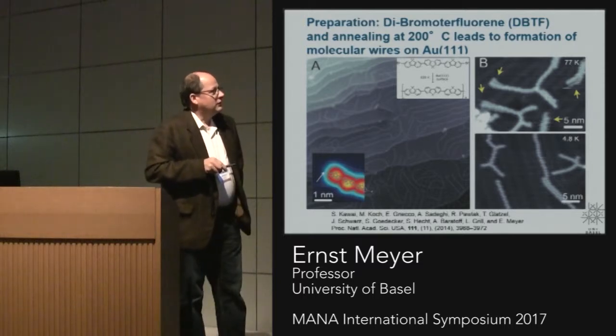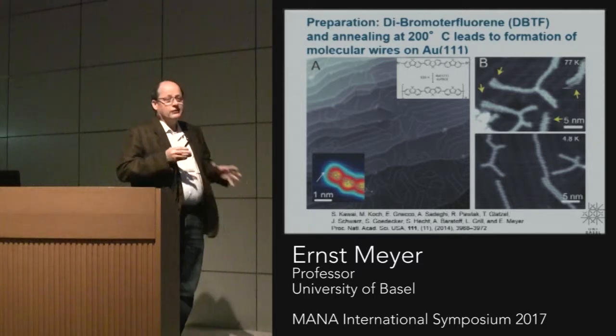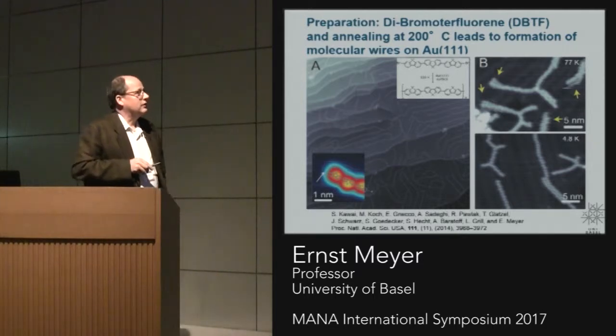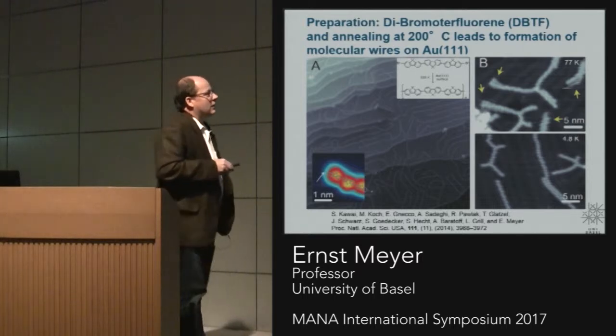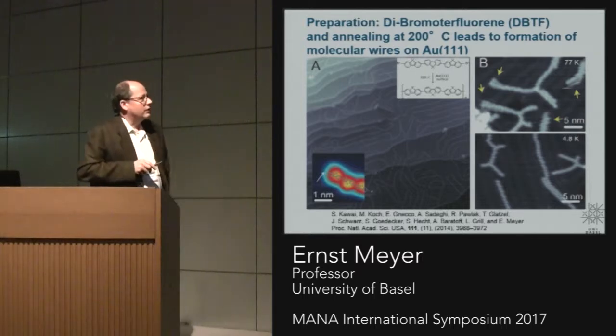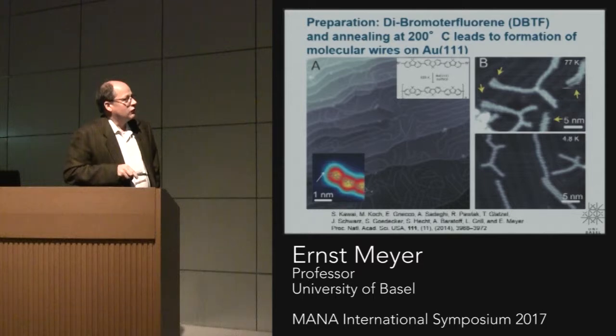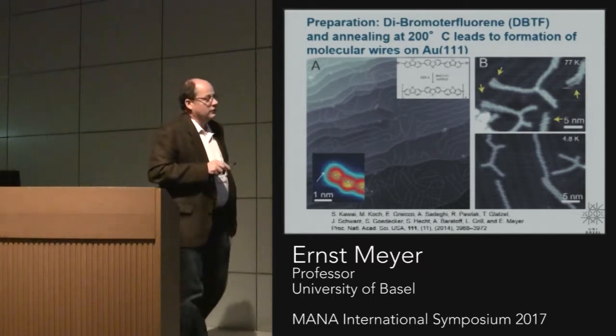If you measure at 77 Kelvin, you see already they move a little bit. So there is some thermal motion going on. It also means they are not very strongly attached, or the diffusion barrier is relatively small. And if you measure at 4 Kelvin, they are basically stable.